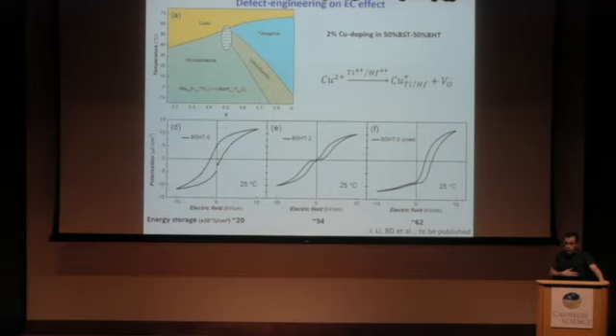What we can also do is to play with disorder. And this has been nicely presented yesterday, I guess. It was a long day already, by Tadei, when he showed how he can play with the doping on the domain walls. And actually, defects in ferroelectrics have been used in many, many applications for hardening ferroelectric polarization, etc., etc. And here we can do exactly the same things. So in this case, for instance, we took this composition, and then we add some copper inside. The copper coupled with the oxygen vacancies to make a permanent dipole, a defect dipole.